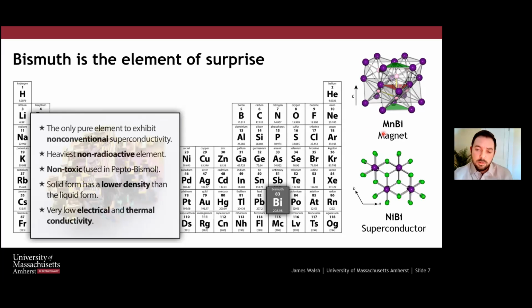Two that I'll highlight just here are the manganese bismuth intermetallic compound, which is a permanent magnet. Actually, at one point, it was the best permanent magnet we had in the 50s, just before the discovery of the rare earth magnets. Manganese bismuth was heavily researched as a permanent magnet. Another example would be nickel bismuth, which is a superconductor. It has a transition temperature of around 4 Kelvin, so it's not really used industrially, but still it's an interesting, relatively high temperature transition. So there's clearly something special about bismuth, and that's the reason a lot of people are interested in these bismuth containing compounds.